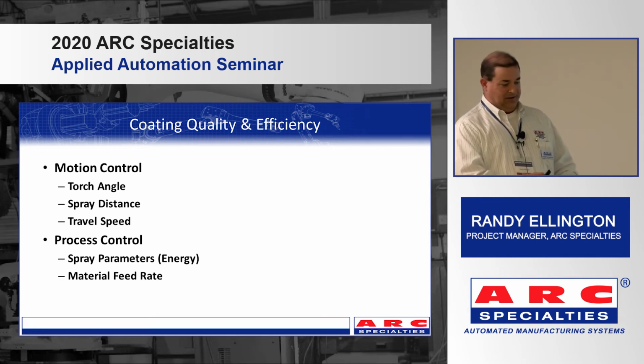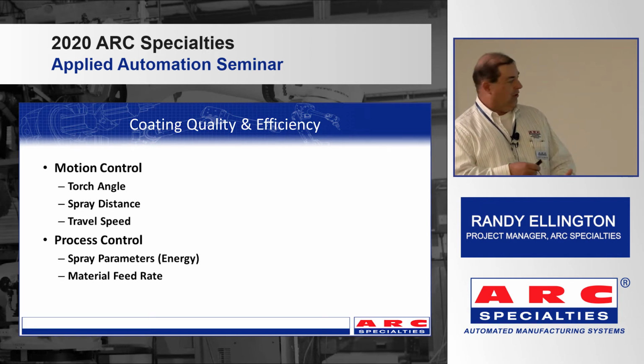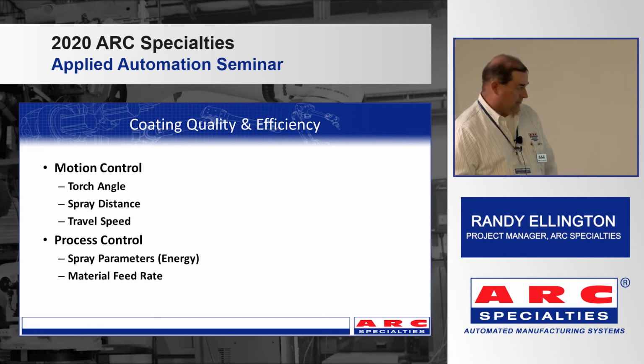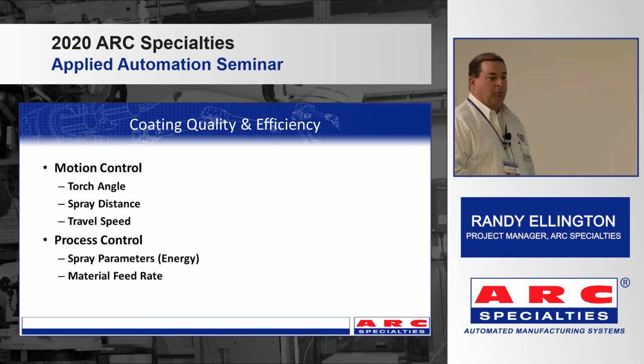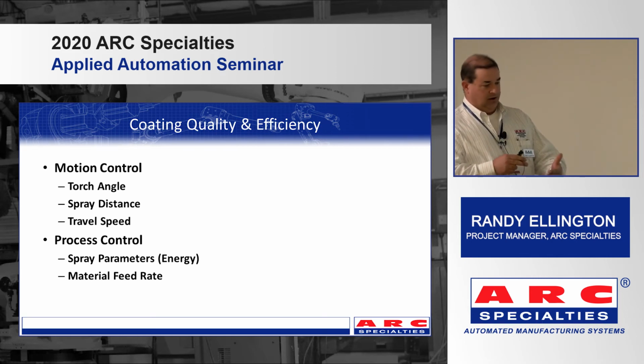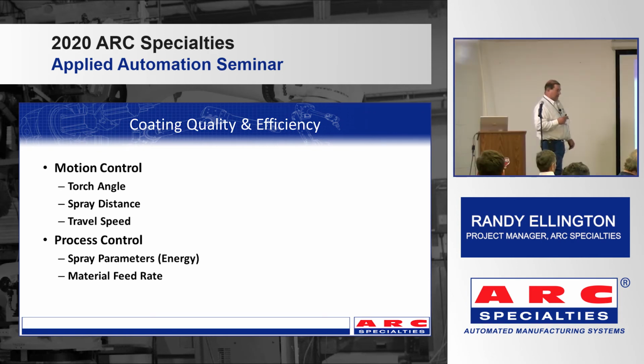So you do it by hand, where you can't really control all these things really tight, and that drops even lower. So it's really important to control your torch angle, 9 degrees. You get off that much, then it changes everything. Your DE drops, your porosity goes up, your hardness goes down, all the bad things.